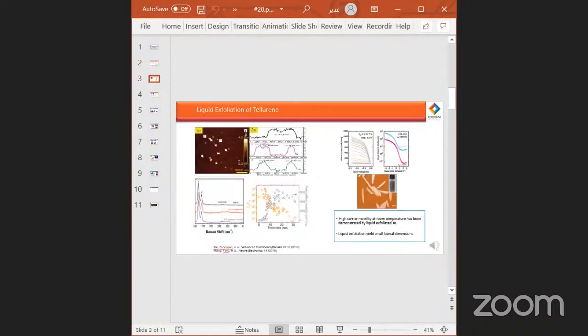Although liquid exfoliation is a valuable solution, the small lateral dimension required new fabrication techniques to study the Te nanosheet properties. In this image, we can see Te flakes from a solution, and we were able to get relatively large flakes a few nanometers thick. But in our approach, we are aiming to have a single flake that can be tuned in its band gap and to compare its physical and electrical properties from bulk to few nanolayers.